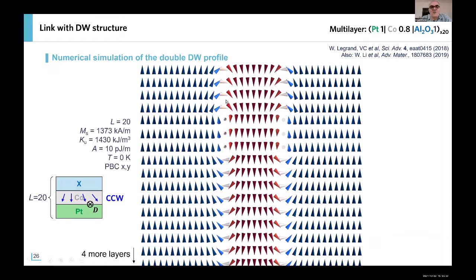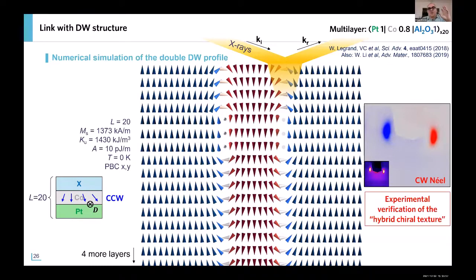So it means you have opposite effective chirality and even a change of the nature of the wall, which becomes a Bloch domain wall or Bloch skyrmion in the center of the nucleus. And because in the XRMS experiments we probe only the top layers, it explains why we do not have a change of the dichroism when we change the stacking. So this demonstrates that in fact, in large numbers of repetitions, we do have tubular skyrmions, but with a twisted chirality, and that's what we call hybrid chiral texture. And this was the first, let's say, path towards more complex three-dimensional spin texture.